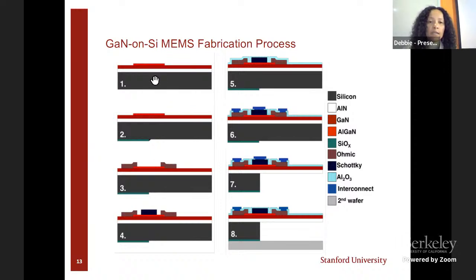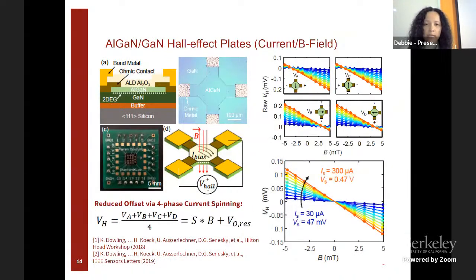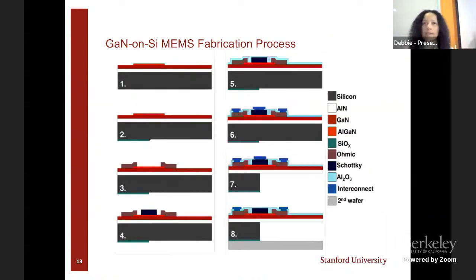You can etch the mesa structure, put down high temperature ohmic contacts. There's a lot that goes into that. Gate contacts, we've explored a variety of high temperature gate contacts, and then a passivation layer, we're using aluminum oxide. And when you start to stack up these materials and operate at high temperature, you start to think about how all of these materials work together. Interconnect material, masking for the backside, release of the backside, and then you have your nice device. And so all of my students can piggyback and yes, go ahead.